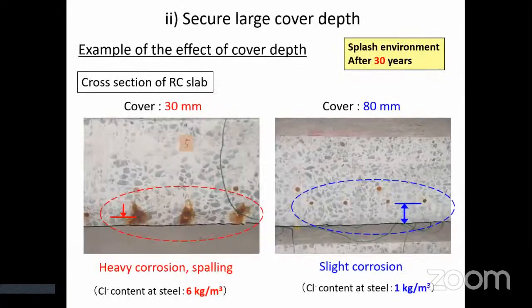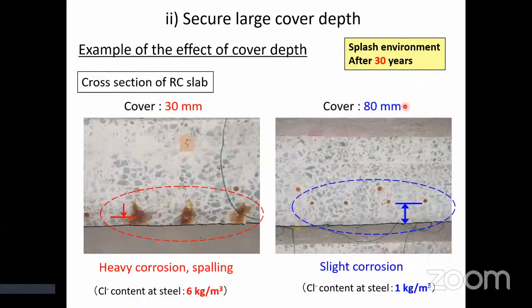Next one is securing large cover depths. This is a basic method, but very effective. This picture shows a cross-section of an RC slab. For example, in the case of 80 mm cover, slight corrosion occurred. On the other hand, in the case of 30 mm cover, heavy corrosion and spalling occurred.